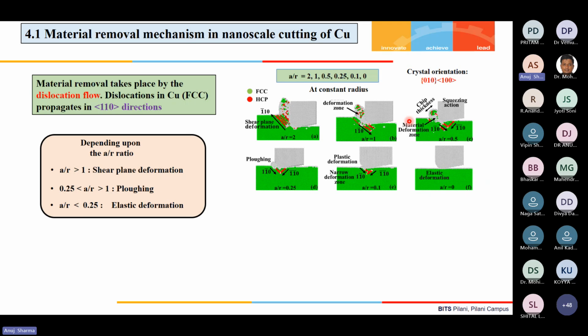In every A/R ratio, the radius is the same. We are changing the uncut chip thickness, so it is being reduced. Initially there is shear plane deformation, and after that an extrusion mechanism takes place. Some of the material goes beneath the cutting tool, and once the uncut thickness is very much reduced, then only elastic deformation takes place. Now no cutting is taking place, only the rubbing phenomenon is happening.